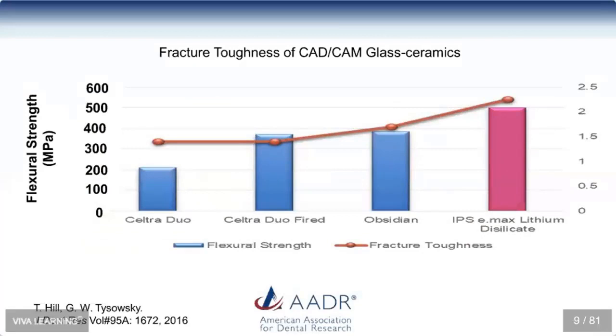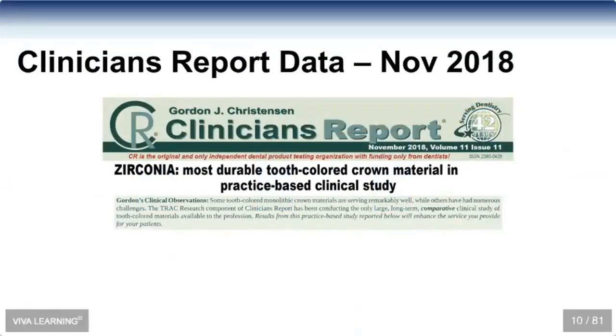When you look at a research piece presented at the AADR, you can see on the far right that Emax lithium disilicate has higher flexural strength, but more importantly, it has the highest fracture toughness of all those lithium silicate materials. In fact, by adhesively bonding Emax, you can increase that fracture toughness even more. We'll explain how that works when we talk about why we want to adhesively bond some of these restorations into place.